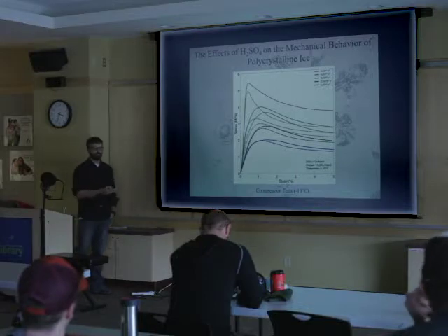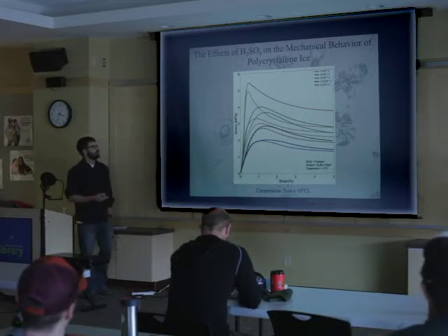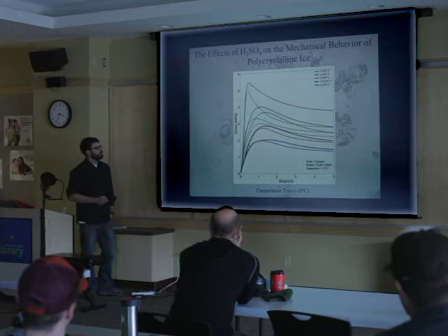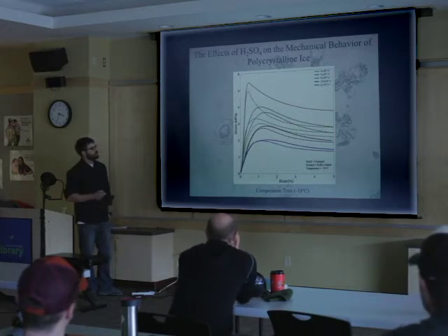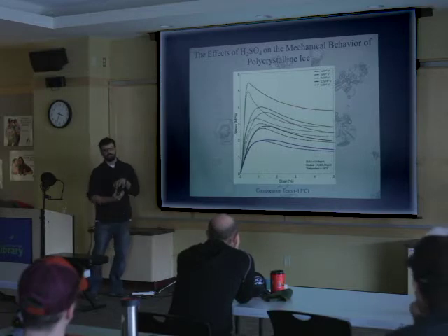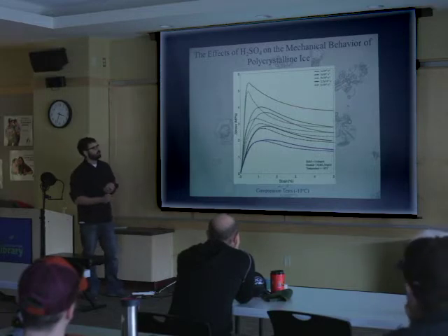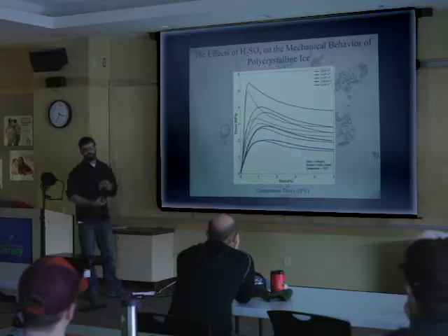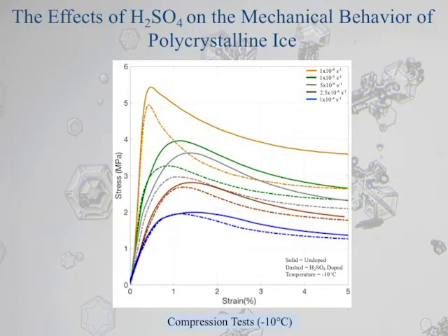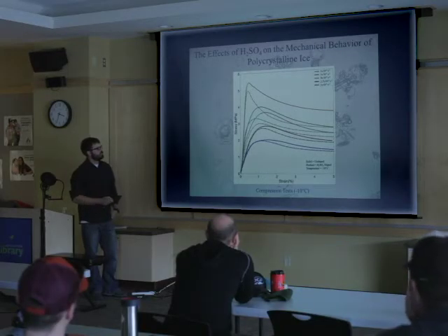These are just going to be your standard engineering stress-strain type plots. Each color here is linked to a different strain rate that was applied to the cylindrical specimen in compression. This 1 × 10⁻⁴ per second is less than an hour, a really fast compression to 5% strain. This 1 × 10⁻⁶ per second is more like 13 hours to get to 5% strain, so a much slower rate of compression. That was the blue down here, the really slow one, and the really fast one up here.